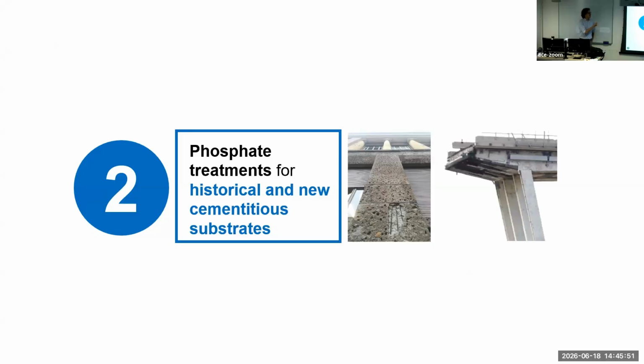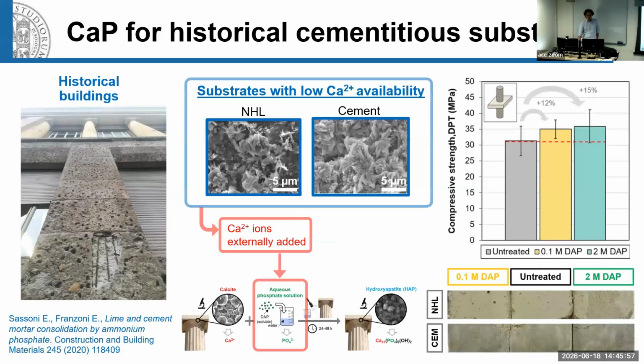Okay, so taking inspiration from the good results we found on stone, the idea was, let's try to transfer all of this to cement. So the first step was considering cementitious mortars, with or without steel bars, as you can see here, that were constructed about 1 century ago or so.